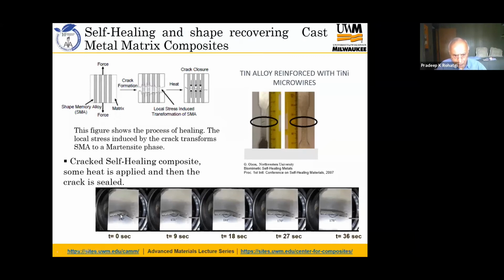Another application: in tin bismuth, I have incorporated long fibers of shape memory alloy and put it in a bending machine, so the bar is bent and there is a crack in here. If I heat this, because of the shape recovery of nitinol, this bar, as you can see as I moved, after 36 seconds has straightened and the crack has shut. So it shows the ability to produce materials with shape recovery and crack closing abilities, or self-healing abilities.